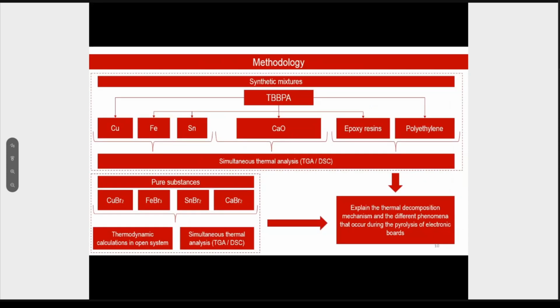So in this study and in this article, I'm highlighting the part related to understanding the mechanism of reaction or the thermal degradation of printed circuit board. This is done by first using a synthetic mixture of the flame retardants to understand whether they interact with different components of the electronic board. This includes metals like copper, tin, and iron, metal oxide like calcium oxide, and also the organic part that includes epoxy resins and polyethylene. Then using the TGA DSC, we also simulate the pure substances composed of the metal bromides that might form from the reaction of the released hydrogen bromide and its interaction with the metals or the metal oxide.